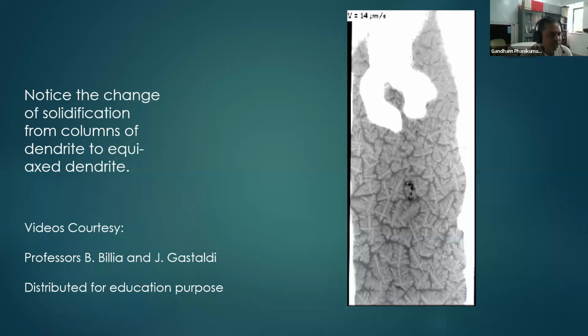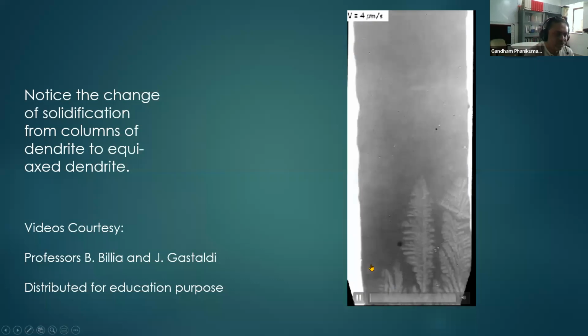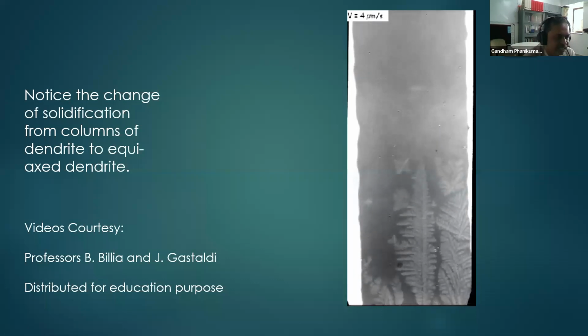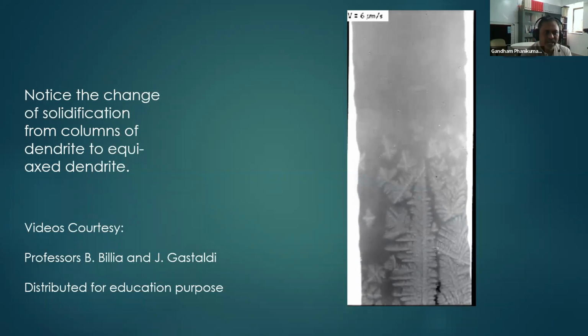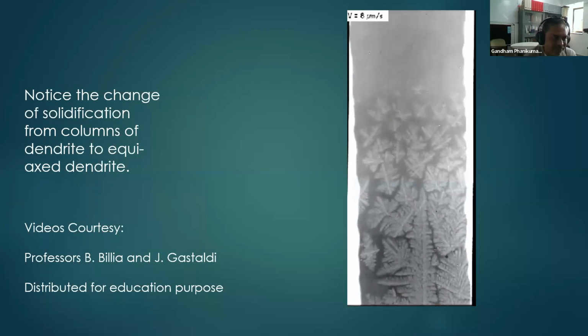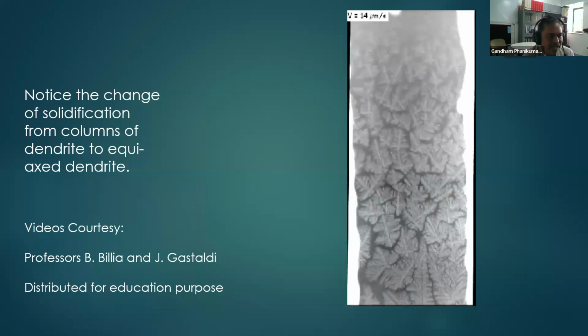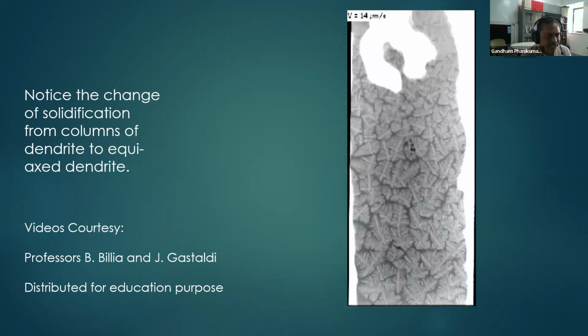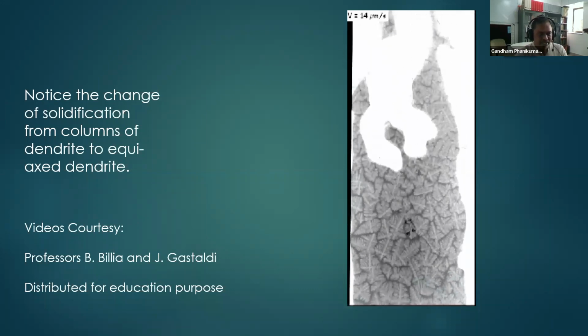So maybe I should tell you how this is done. This particular visualization was done with a thin 150 micron aluminum alloy sheet kept between two graphite sheets, and then they were held by a boron nitride capsule around it, and then kept in the path of synchrotron radiation. So what happens is that sometimes the grains are stuck to the wall, and some of them are nucleated between the walls, and therefore they are free, and they fall in the liquid. So if they are not falling, it is not because there is an opposing force. They are just nucleated on the wall, and therefore they are stuck on the wall. That's all. Okay, that's the only reason.